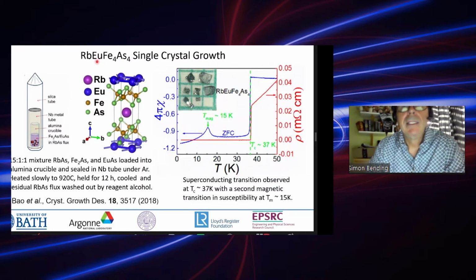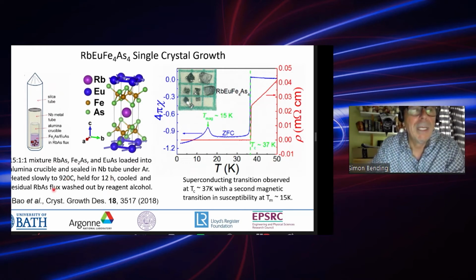So more then about the rubidium europium iron arsenide material itself. The single crystals were grown by heating a mixture of rubidium arsenide, iron arsenide, and europium arsenide in an alumina crucible, which was sealed in a niobium tube under argon, heated slowly to 920 C, held there for 12 hours, and then cooled, and any residual rubidium arsenide was washed out by reagent alcohol. All the details are described in this paper here.